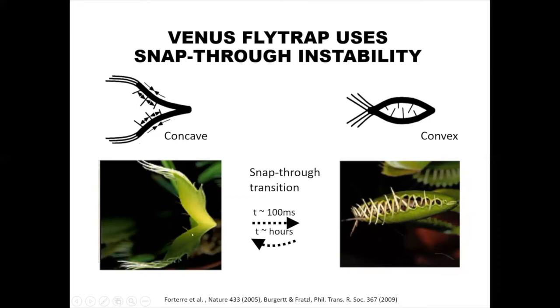When a little animal or bug touches these hairs, I don't know if you can see them, they're very tiny hairs, they are under tension. If they are touched, the whole concave shape snaps into a convex shape. This happens within 100 milliseconds, and it traps the bug. To recover from the convex to the concave shape, water swelling and shrinking, or turgor, is used. To reopen the Venus flytrap, there is swelling and shrinking of the adjacent cell layers.